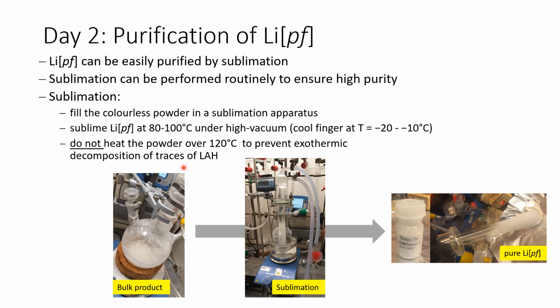It's very important to not heat the powder above 120 degrees because at this point the lithium aluminium hydride can decompose exothermically in an explosion. At the end, we should get a colorless, nice powder of a pure lithium salt.